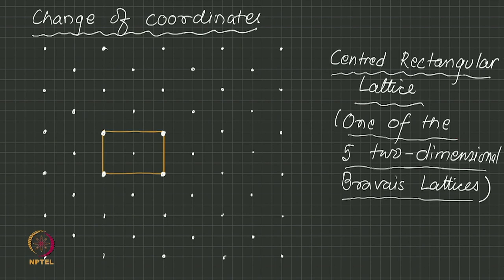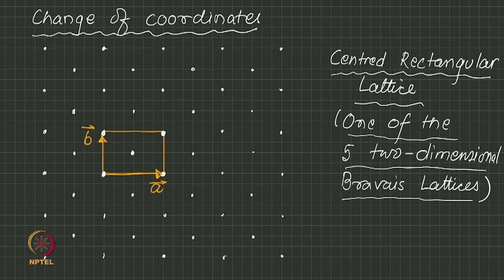Here there is a rectangle that has a lattice point not only at the corners but also one at its center. Obviously, if this is the unit cell, the corresponding crystallographic coordinate system will be the edges of the unit cell — this is the so-called conventional unit cell of this lattice. The conventional unit cell is defined by one basis vector along one edge of the rectangle and another basis vector along the other edge. So a and b are the conventional crystallographic coordinate system of this lattice, but the cell they generate is centered, meaning it is not a primitive unit cell.